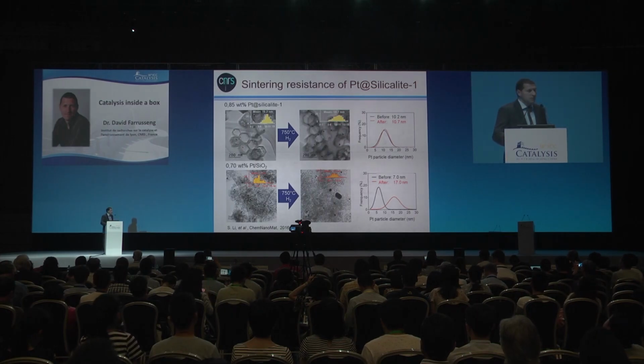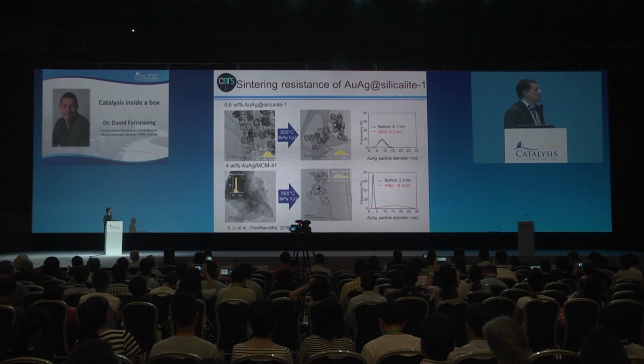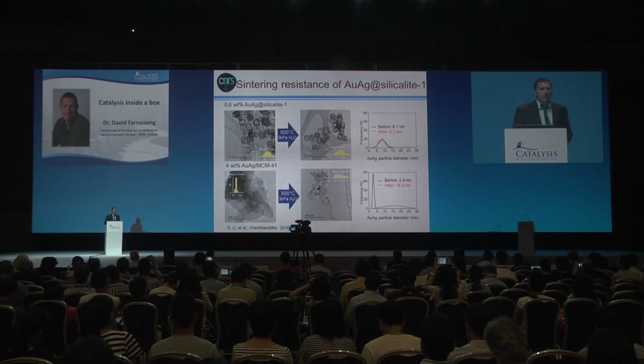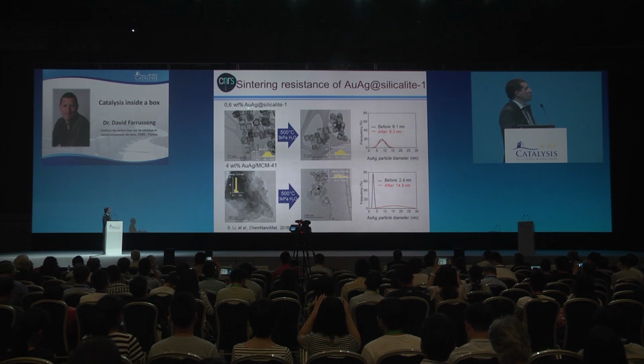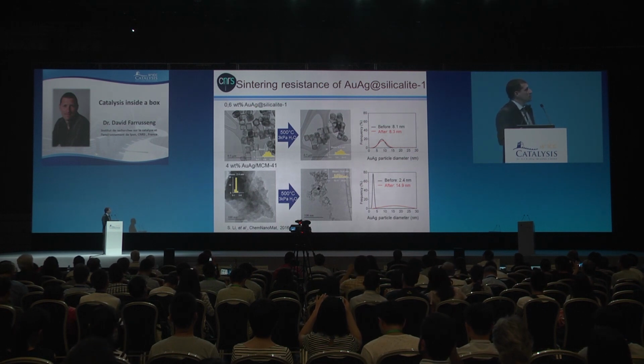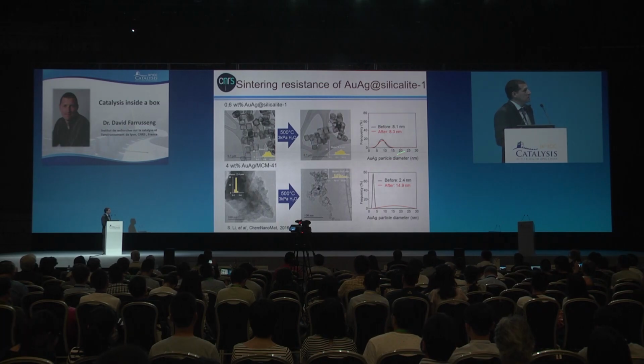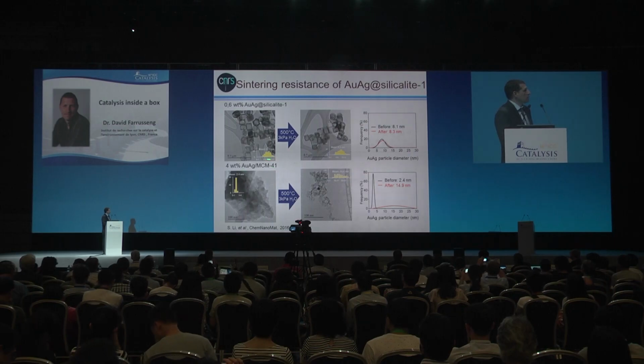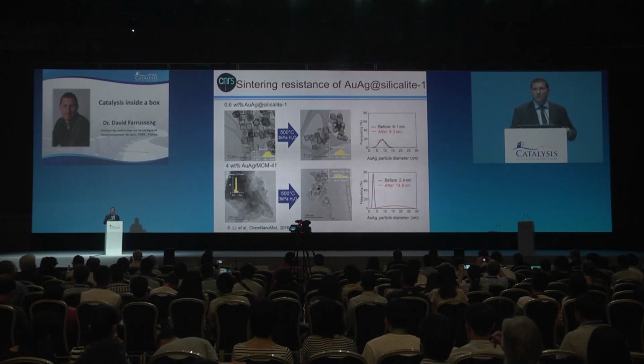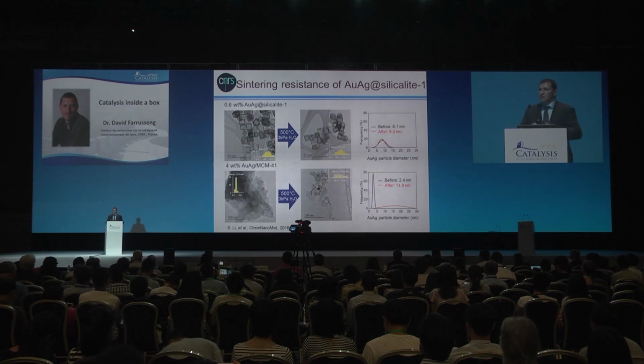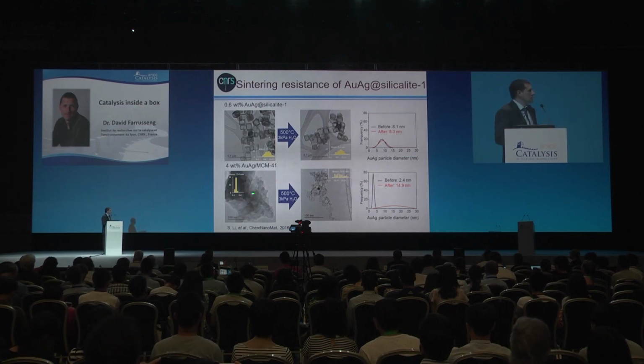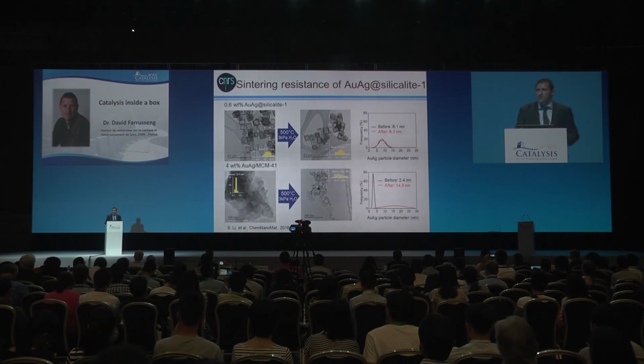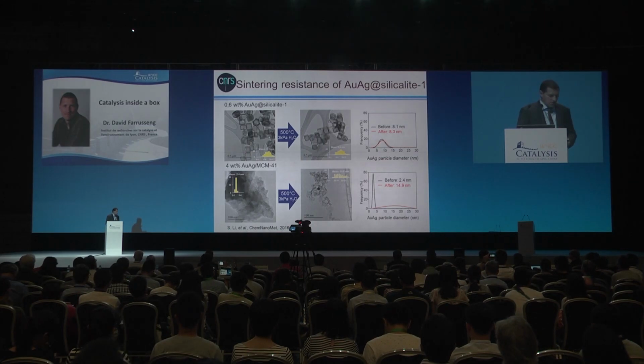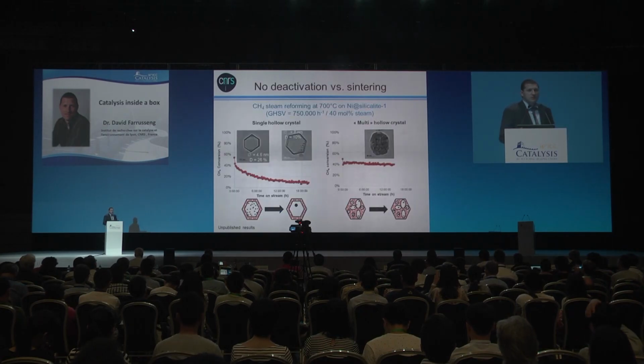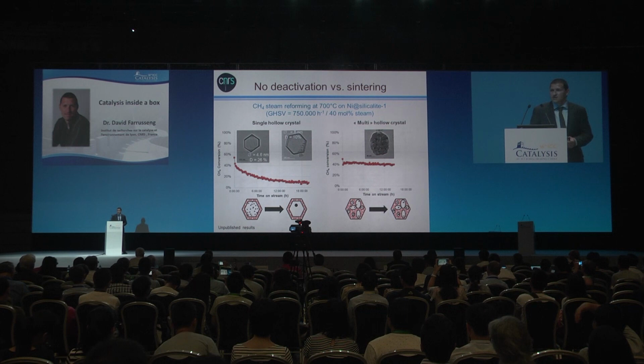But that might not be a very harsh treatment. Water is known really to promote more sintering. And for this one, we have selected the gold-silver case, and you see here hardly any change after this steaming treatment, whereas in the case of encapsulation in MCM-41, which you might think also prevents a particle from sintering, this is not the case. The MCM is completely destroyed by this quite moderate steaming treatment. But maybe some of you are not yet convinced about the stability of such materials.